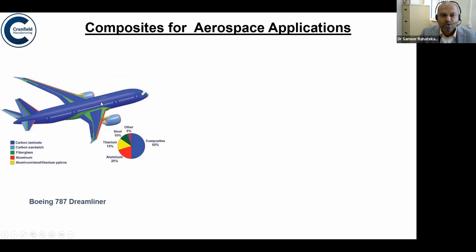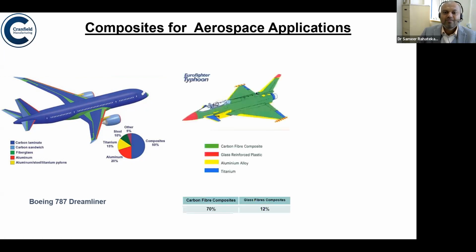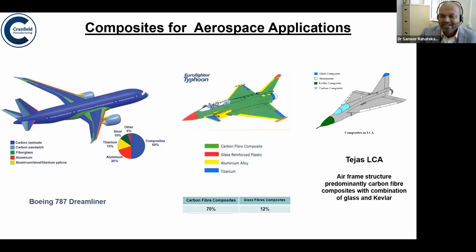Okay. By volume, it's much, much more, but you can see pretty much everything is blue except the engines. That's because most of the material used in new generation of aircraft is composite materials, lightweight structure. If you look at a defense aircraft like Eurofighter Typhoon, more than about 70% by weight is carbon fiber. Okay, and remaining 12% or most of it is glass fiber. Only the engine part is made from titanium or aluminum alloy. Okay, same with some other aircraft beyond Eurofighter that also has a large component of it manufactured using carbon fiber and Kevlar fiber as well.